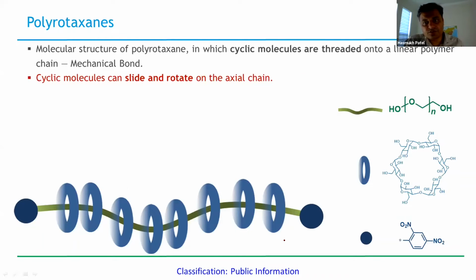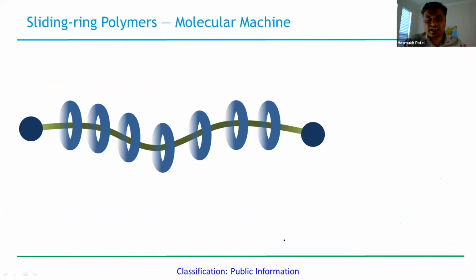However, one point we need to make sure of is that such a Polyrotaxane as it is, is inactive. The reason is that on each cyclodextrin, the cyclic molecule, the outer side is a highly hydroxylated compound. So once we synthesize these materials, they form hydrogen bonding between each polyrotaxane, and that's why there is no movement of the cyclic molecules, neither sliding nor rotating. So it is very important to make it functional or movable. We need to functionalize these cyclic molecules with some other functionality so that the movement or sliding will be easy.